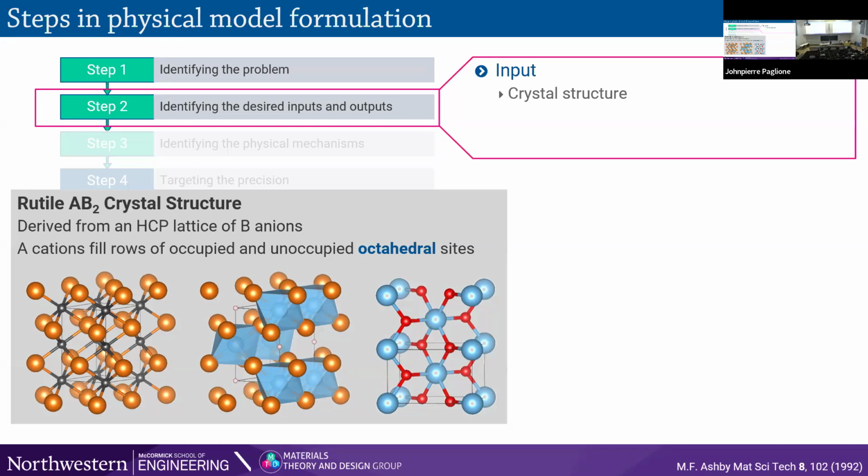And now if I occupy those octahedral voids with cations, but in an alternating fashion, so I have a row here and a row here and a row like that, and I alternate, and leave the other row vacant, I generate the rutile structure, which comprises metal ligand octahedra, which are edge shared and form infinite one-dimensional chains. And that's what this structure is here.